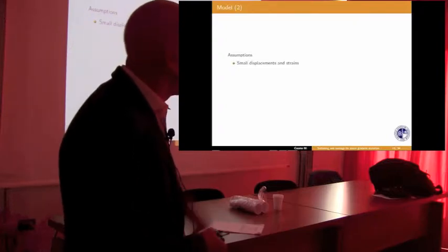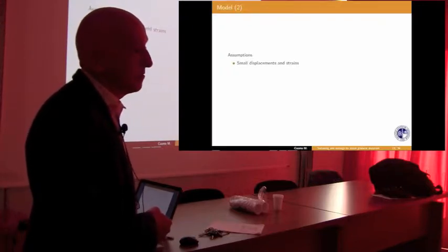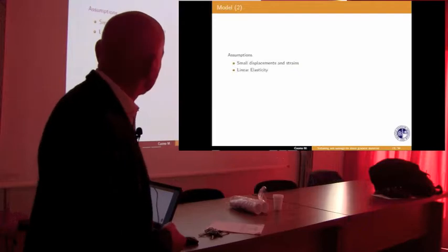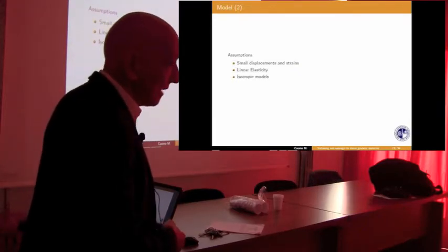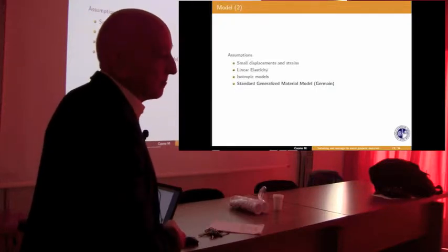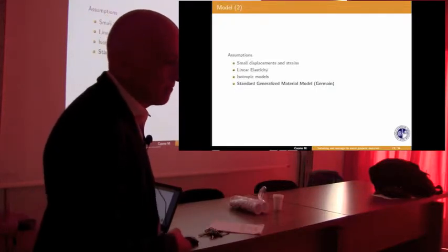The model, first of all, has assumptions and restrictions. I present the model only with small displacement and strains. I know that Professor Bertrand said this is a strong limitation. I agree, as it should be. I present only linear elasticity, only for the isotropic case. I use the standard generalized material model of Germain. So no Piola this time, but the French school.